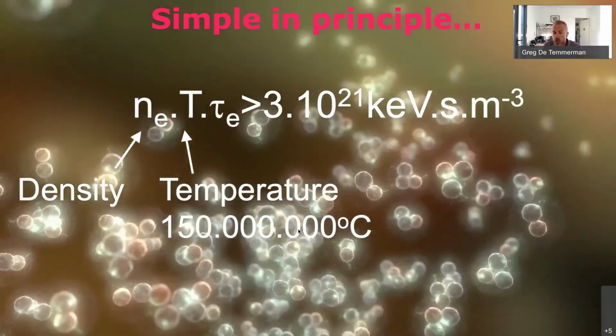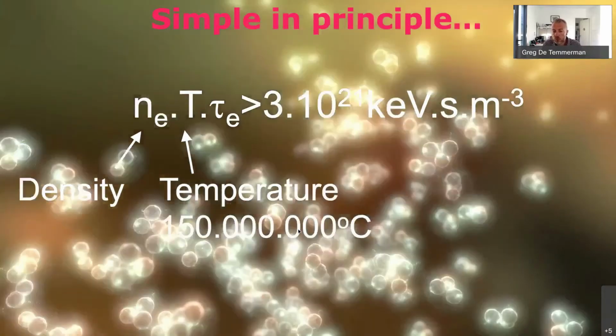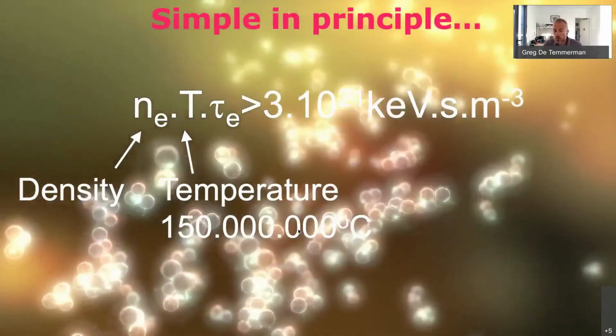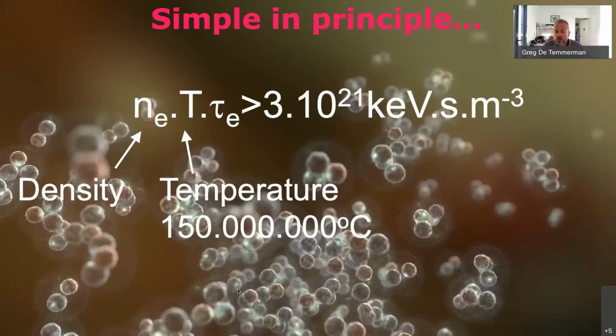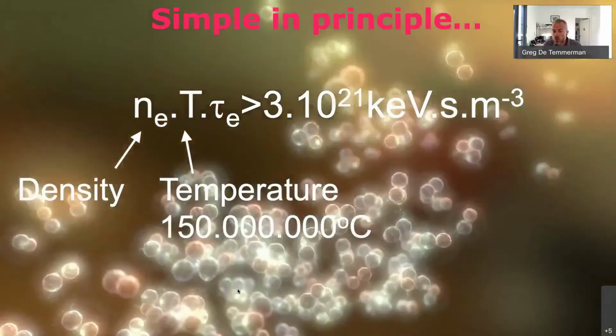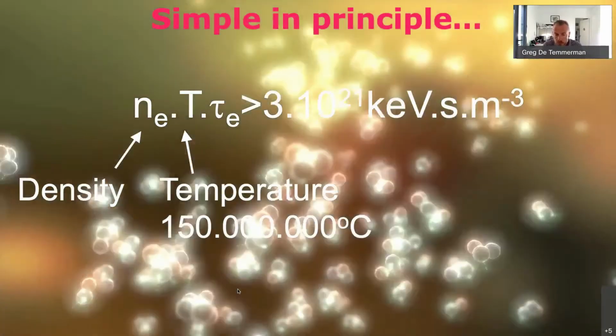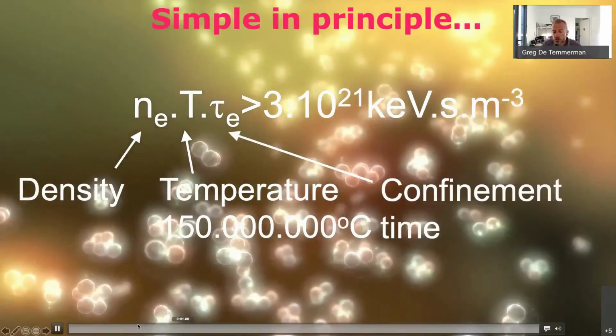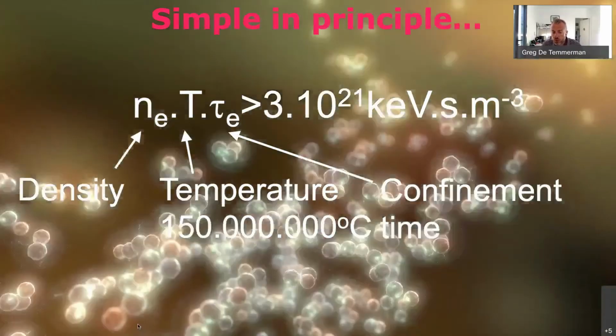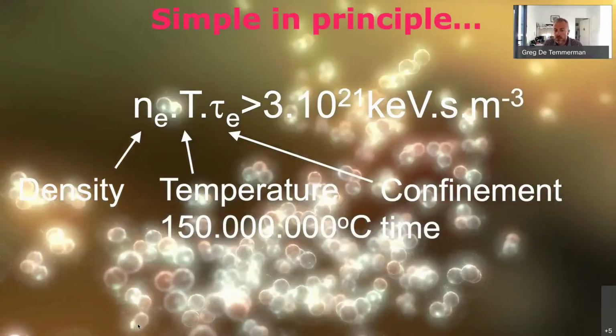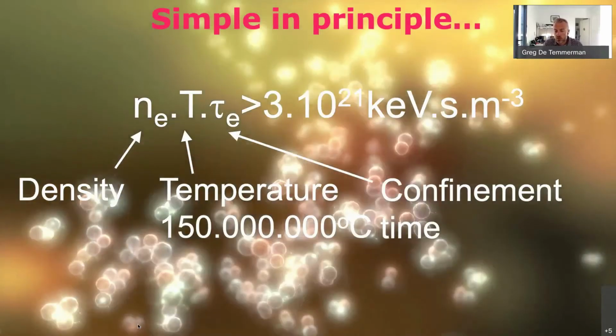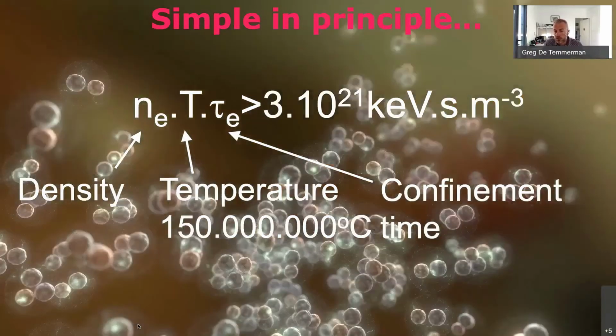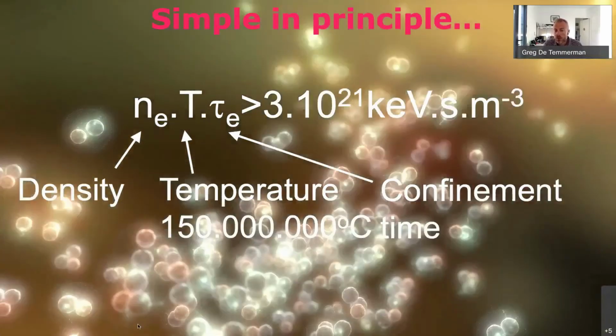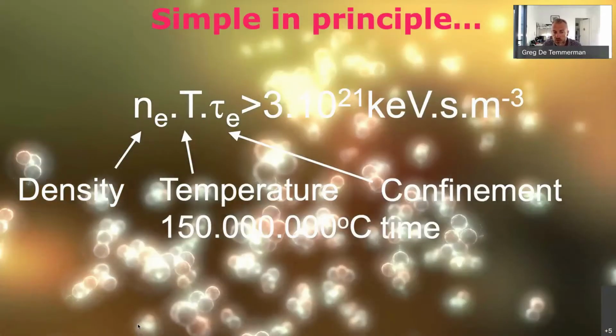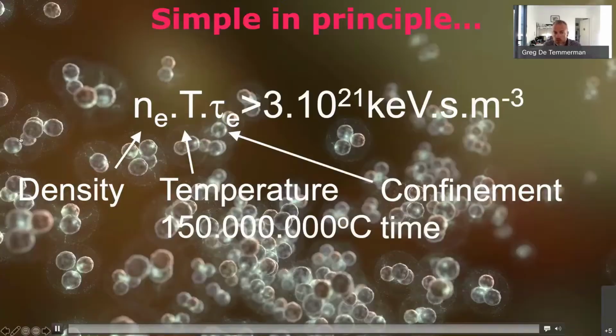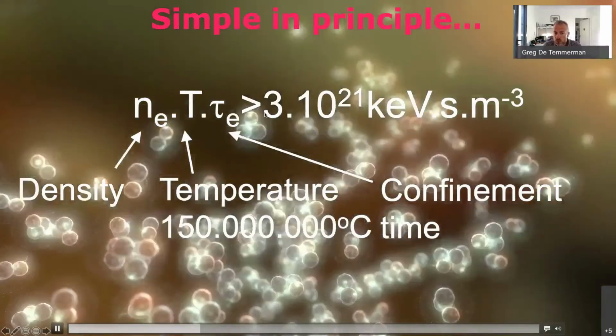And because we work in a gas you have an equivalence between the temperature and the speed at which the particles move. So the hotter we get, the faster the particles move, and the more probability we have to have a high energy collision. And then the confinement time is a measure of the efficiency at which we are actually confining that gas somewhere and it does not leak energy. So you have to make sure that it's sufficiently isolated from the outside so that it can stay hot and can have fusion reactions inside it.